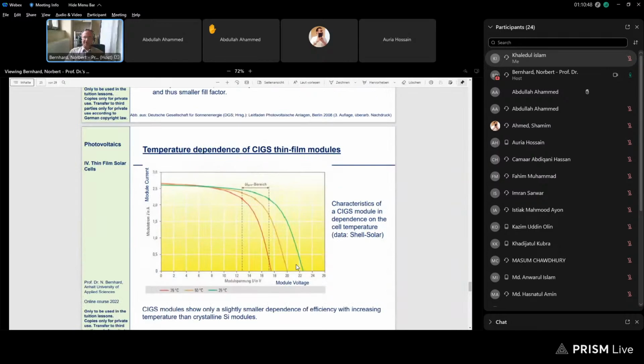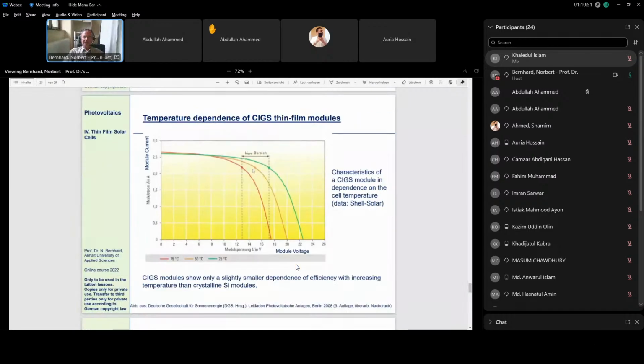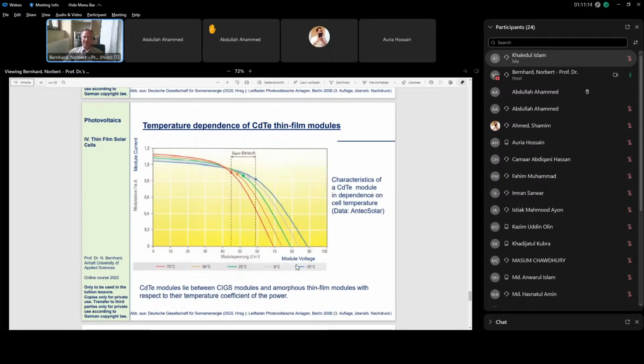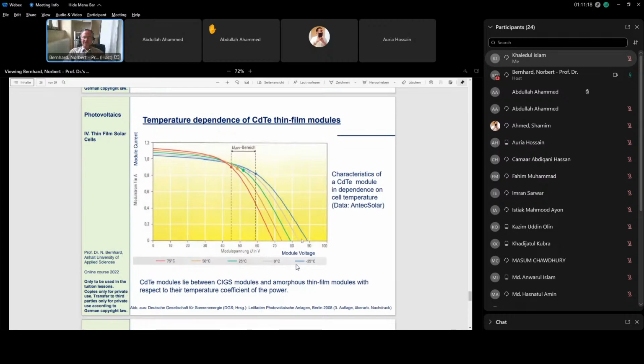Here we see it for the copper indium gallium diselenide. You see the copper indium gallium diselenide looks better than the amorphous silicon, but also smoother than that of the crystalline silicon. Okay, these are just three curves for three different temperatures. Okay, and here an example of cadmium telluride, again at different temperatures. Again we see here the big change of the voltage with temperature. It's a smaller change of the current with temperature, and we again see that the curves are much smoother than those of crystalline silicon, and therefore the fill factor is lower, and therefore the conversion efficiency is less.